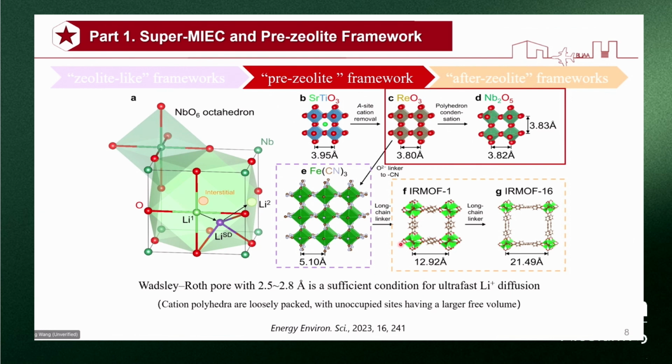So in our paper, we have defined a pre-zeolite framework to mean crystals with the population of open pores with a diameter smaller than the water molecule, around 2.5 to 2.8 angstrom, and therefore it can exclude water absorption and generally all molecular absorptions, while allowing the surface-diffusion-like transport of lithium ions.